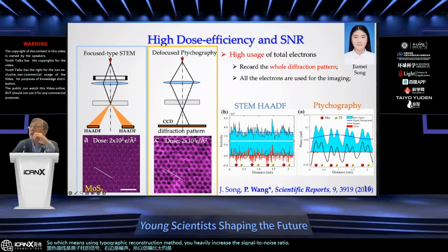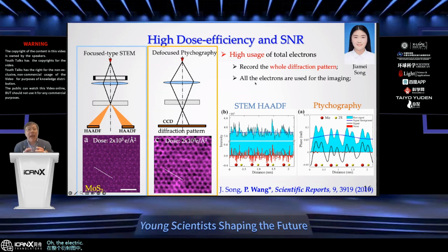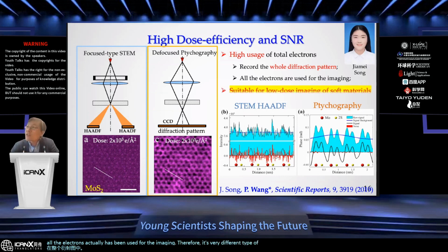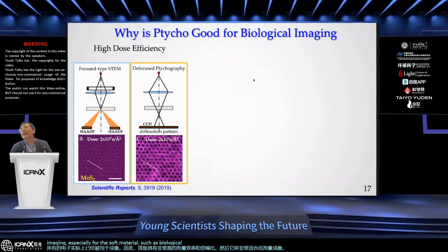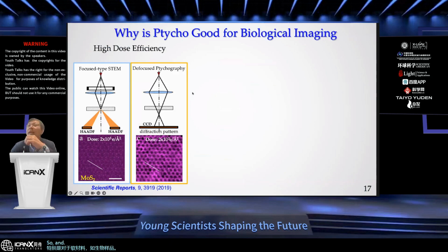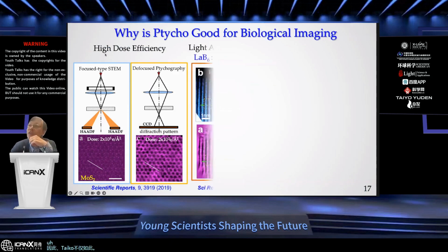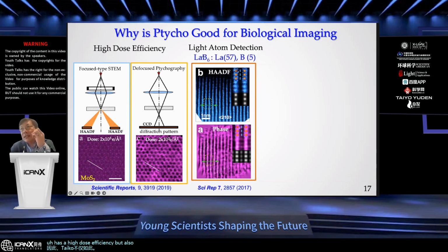That's because you record the entire diffraction pattern, so all the electrons are actually used for the imaging. Therefore, ptychography has very high dose efficiency and signal-to-noise ratio. And then it's going to be very suitable for low dose imaging, especially for soft materials such as biological samples. And ptychography not only has a high dose efficiency, but is also very sensitive to light atoms, as you can see here.